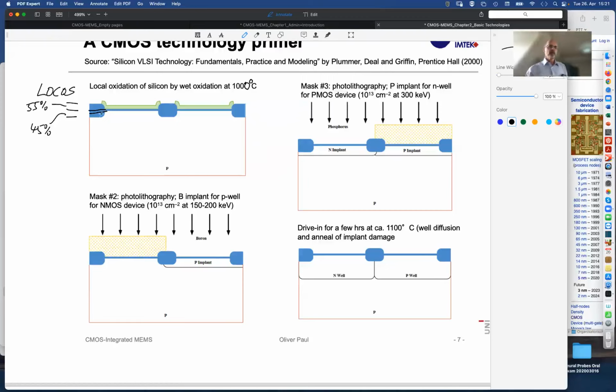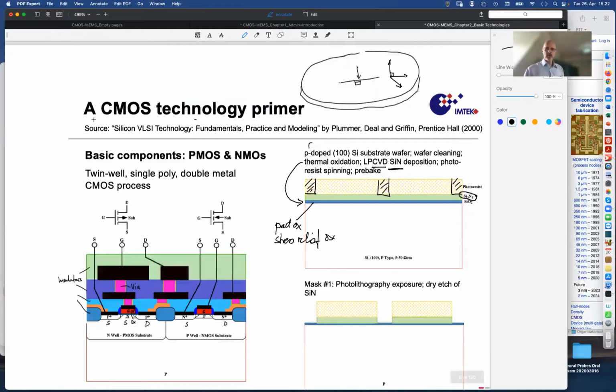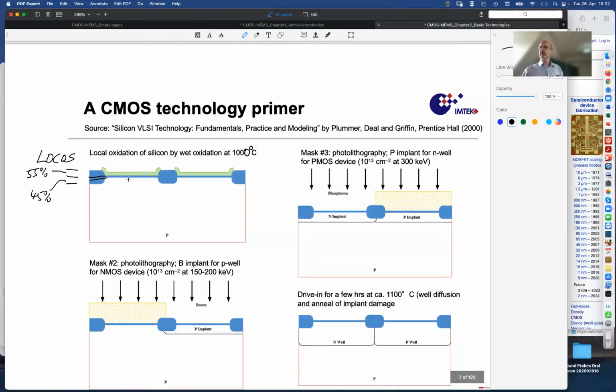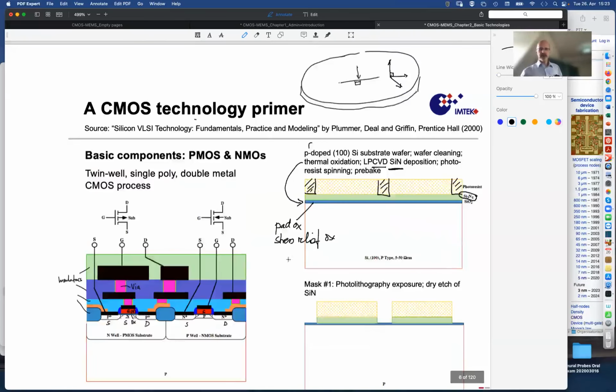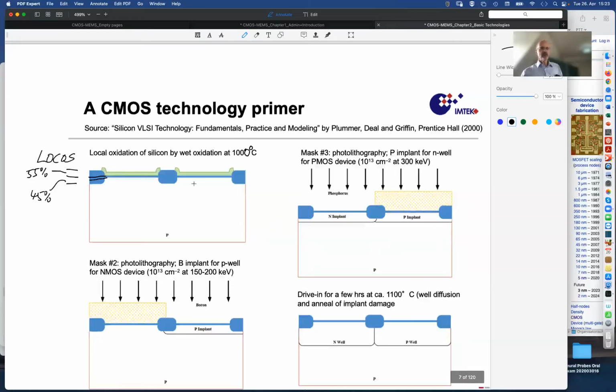So what happens here is that where the silicon was more exposed, namely here, it has grown thicker into silicon oxide. Where it was protected by the silicon nitride, nothing has happened, because the silicon nitride did not let the water molecules through to the silicon to be reacting there. And so this is kind of the mask layer. Like photoresist is the mask layer against some removing process, the silicon nitride is here now the mask layer against some growth of oxide. But you see also that this masking is not perfect. You see the silicon nitride has been lifted up somehow, because the water diffusion does not go only vertically through the oxide, it also goes horizontally.